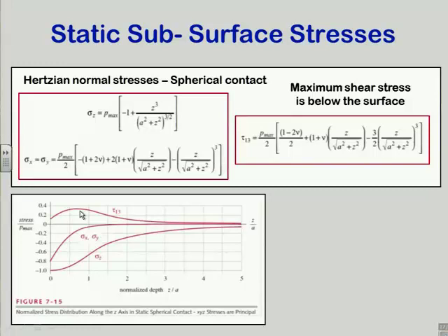where the pit starts. So I've got a high stress and shear in the material, and if there's a little flaw anywhere in that material, that shear stress is going to find it, and it's going to grow that crack and grow that crack and grow that crack until, boop, out pops a divot. And now I've got a rough surface. So now every time that pit comes through, it goes bang, and the thing grows like crazy.